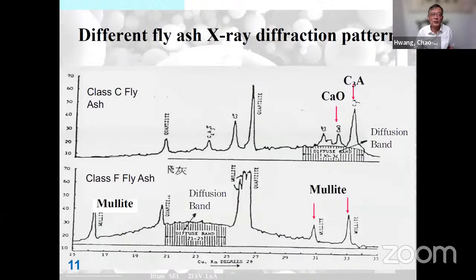And look at the X-ray pattern. The class C fly ash actually has a diffusion band at about 30 to 34, and the class F fly ash has a diffusion band at about 21 to 25. The major composition of class F fly ash contains a large amount of SiO2 and Al2O3, so it's mullite and some quartz. Next, please.